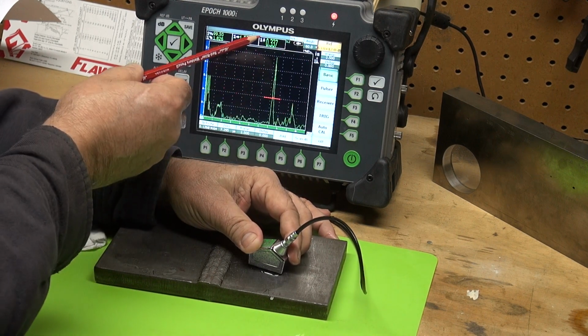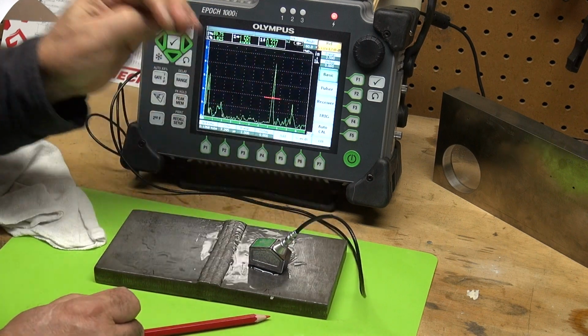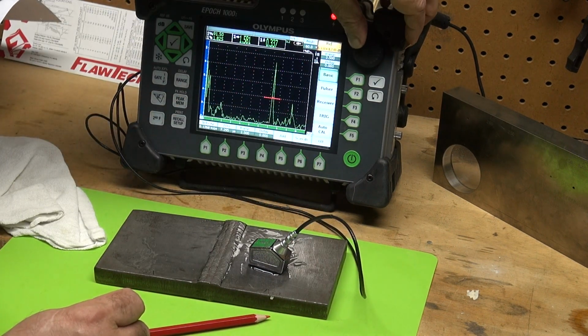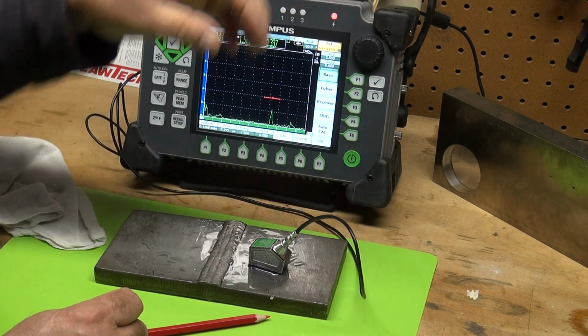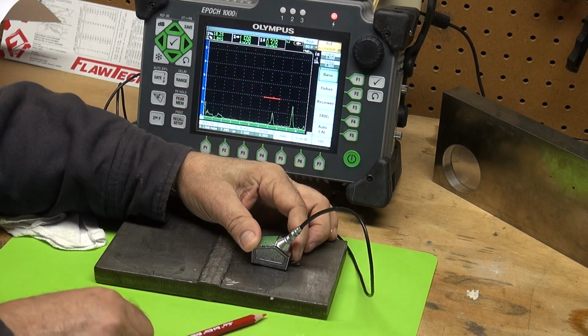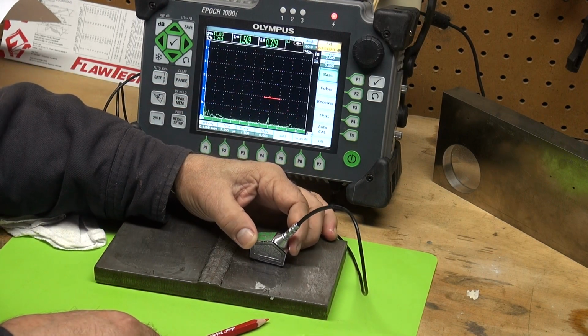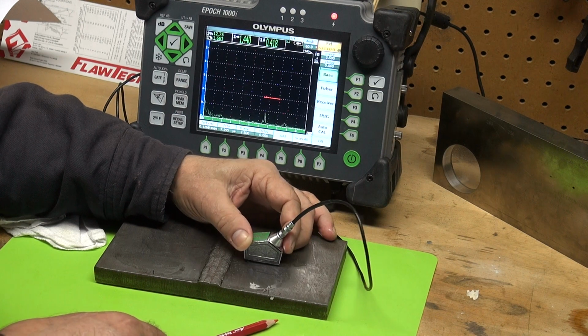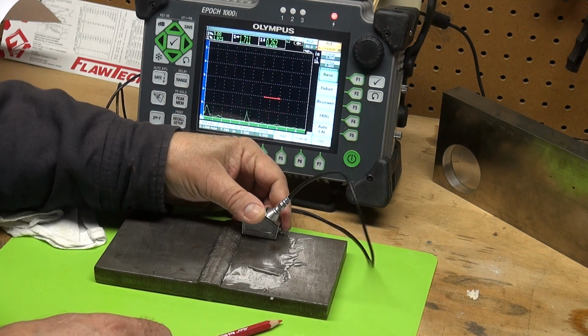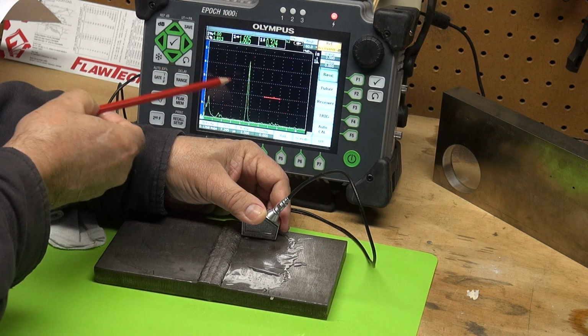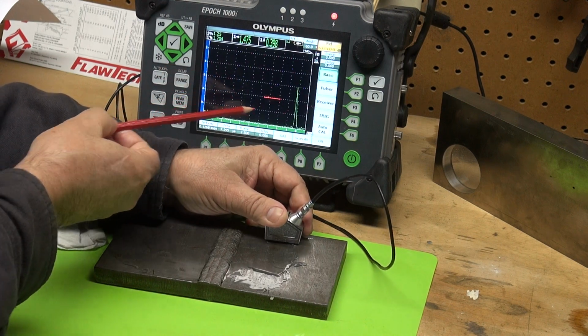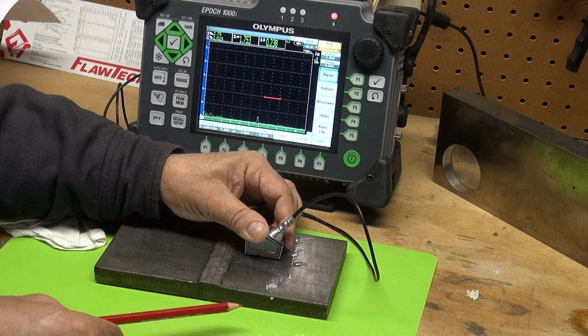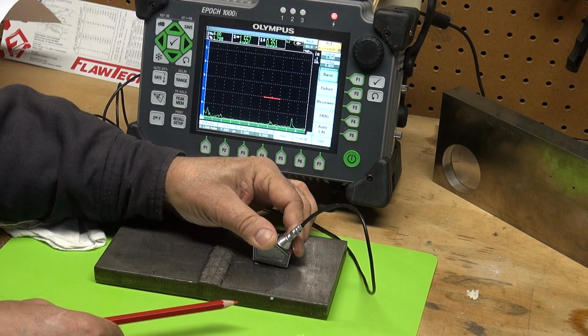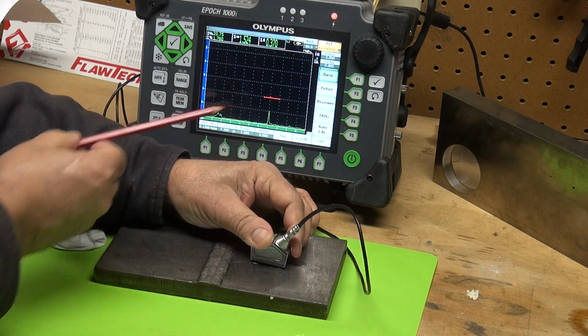Now I'm running 12 dB hot. Let me pull this down to our reference dB where I used the side drilled hole, my reference that I used for the 0.6 deep side drilled hole. And let's look at it. See, my geometry still shows up good. My root, and then the toe of my weld. But see, this slag inclusion is fairly low amplitude.